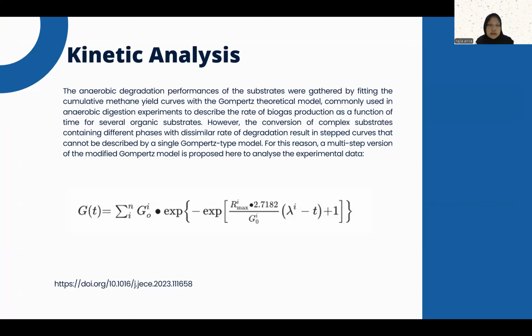So this is for the kinetic analysis. The anaerobic degradation performance of the substrate was gathered by fitting the cumulative methane yield curve with the Gompertz theoretical model, commonly used in anaerobic digestion experiments to describe the rate of biogas production as a function of time for several organic substrates. However, the conversion of complex substrate containing different phases with dissimilar rates of degradation results in stepped curves that cannot be described by a single Gompertz type model. For this reason, a multi-step version of the modified Gompertz model is proposed here to analyze the experimental data.